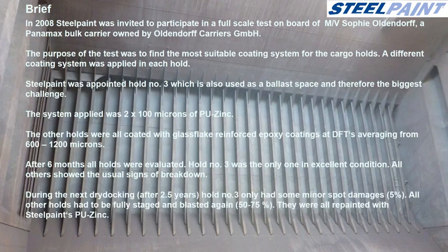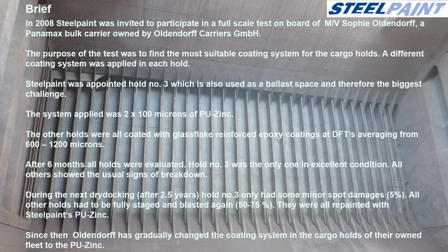During the next dry docking, after 2.5 years, hold number 3 only had some minor spot damages, 5%. All other holds had to be fully staged and blasted again, 50 to 75%. They were all repainted with Steelpaint's PU Zinc. Since then, Oldendorff has gradually changed the coating system in the cargo holds of their own fleet to the PU Zinc.